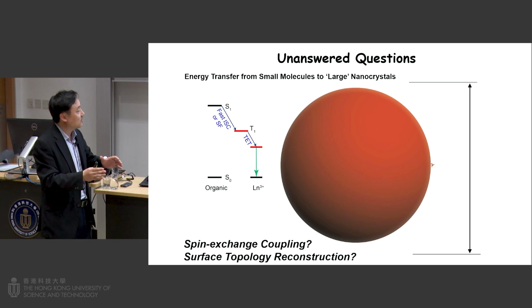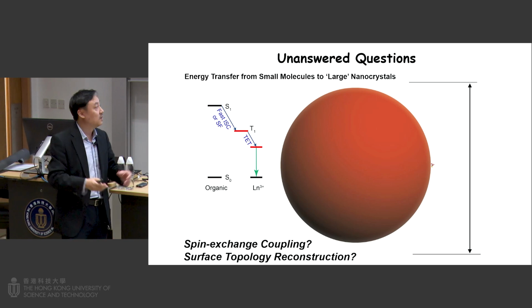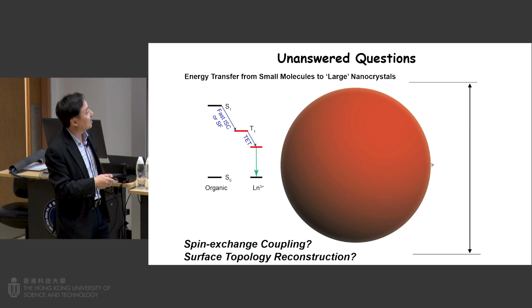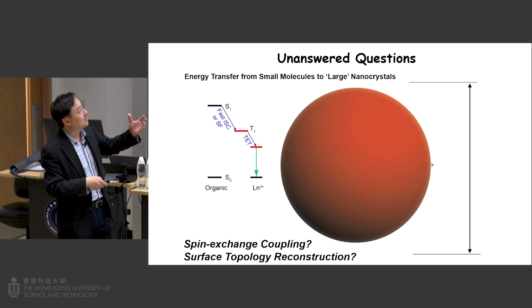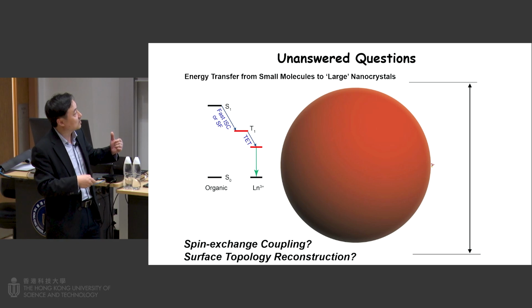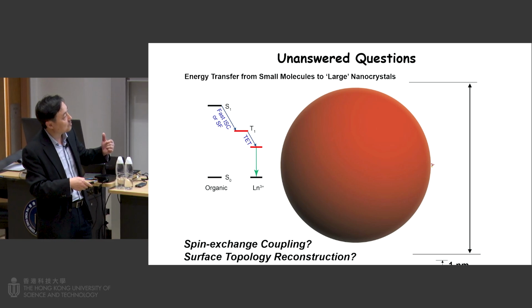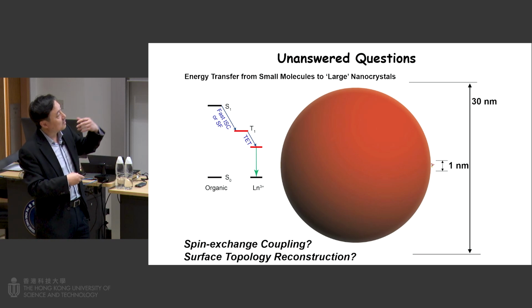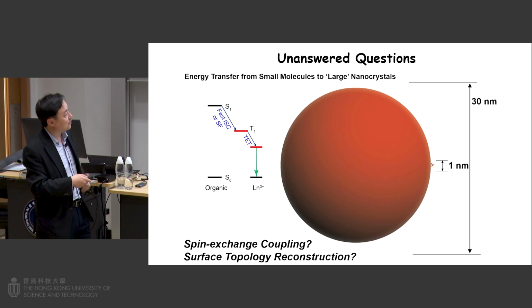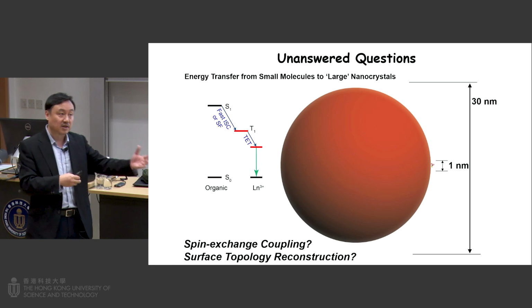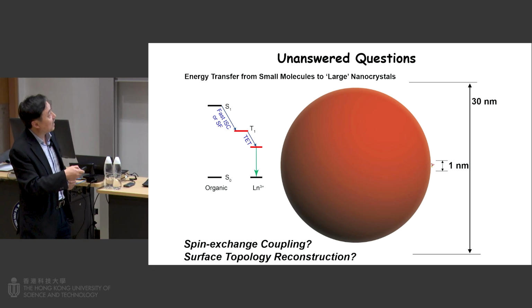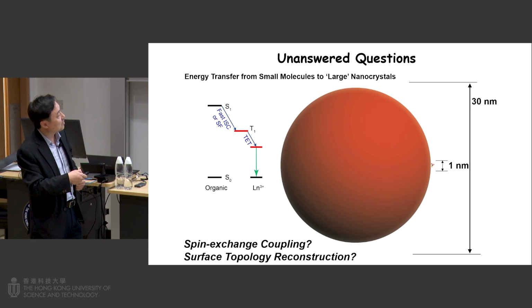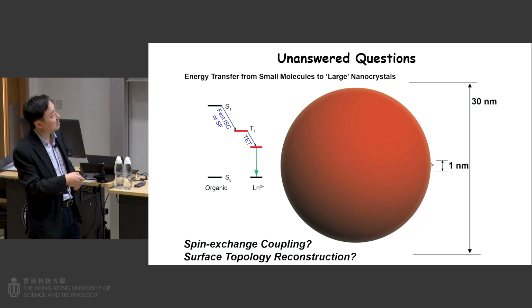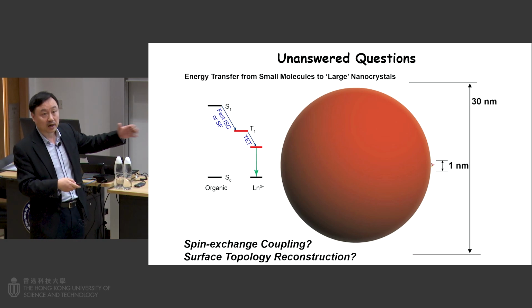For fundamental study, if you're interested in luminescence transfer, FRET, certainly you can consider using these particles, because you can treat the particles as an energy donor. You can study energy transfer from the particles to an organic dye, very small, right here. So how you transfer the energy, how you enhance the efficiency. Normally for FRET, energy transfer is distance dependent. It's less than 10 nanometers. But if your particle is 20, 30 nanometers, how do you transfer energy from this side of the particle to the organic dye across 30 nanometers? Obviously, the distance is too long.